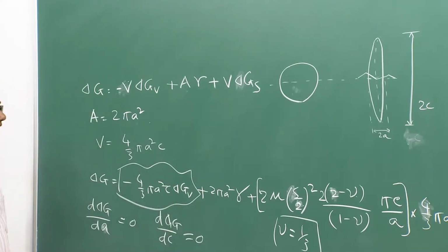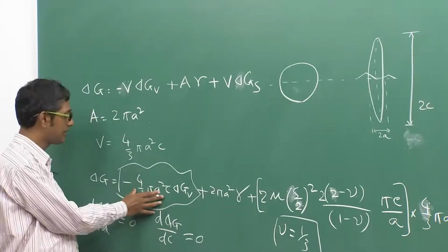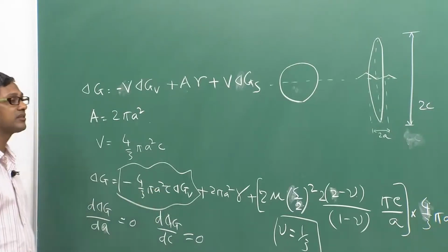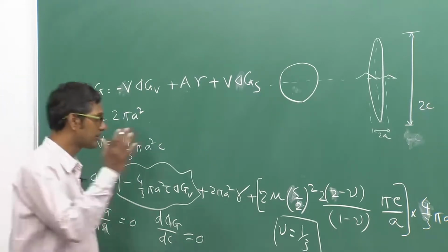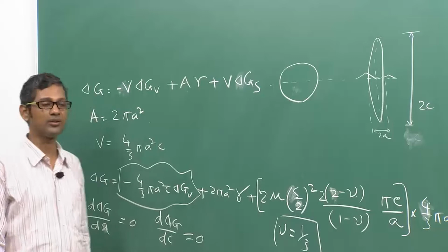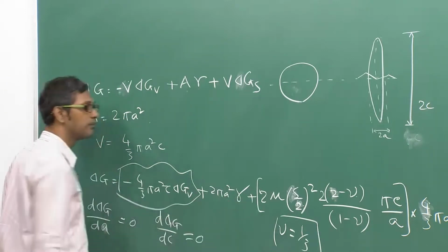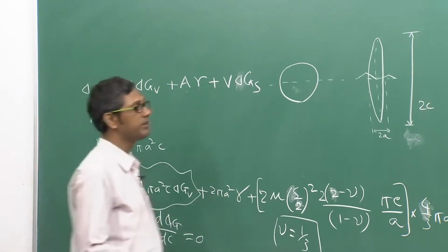And because it is higher, this takes away a lot of the chemical free energy available to the system, and that makes the transformation incomplete even if you quench to liquid nitrogen temperature. And this is the reason austenite is retained in the microstructure. Austenite can never be fully transformed to martensite because of this strain energy. This energy takes away a lot of the chemical free energy.